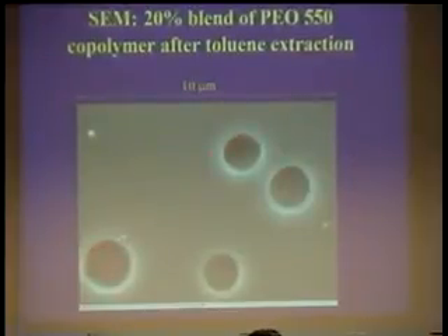And sure enough, what you see here is holes or pits in the surface, presumably where the PEO component has been extracted. And this is 10 microns across, so the pits are 1 to 2 microns in size and diameter, which is typical of microdomains that you find in blends of two homopolymers. So it looks like the blends have this typical microstructure of microdomains of this 1 to 2 micron size. If you do this experiment with the matrix that doesn't have any PEO, then of course it's just a bland surface. You don't see anything.